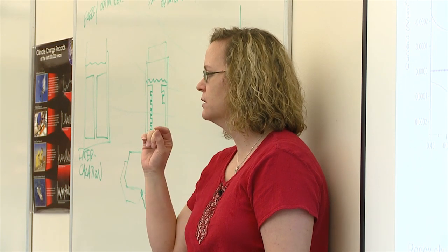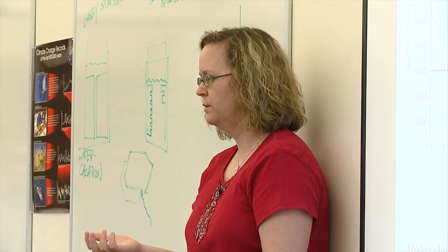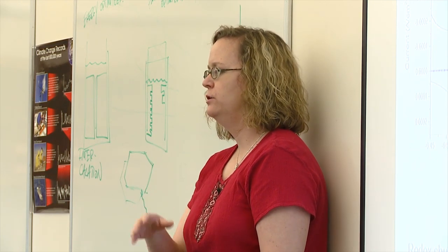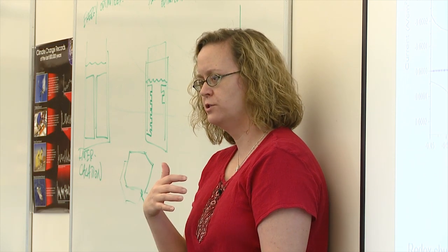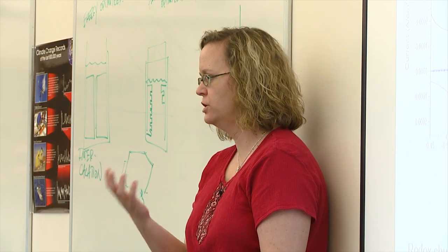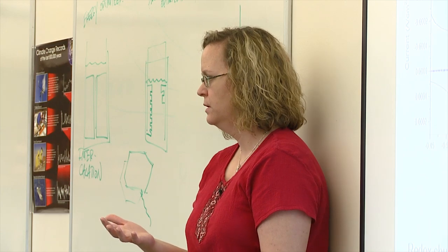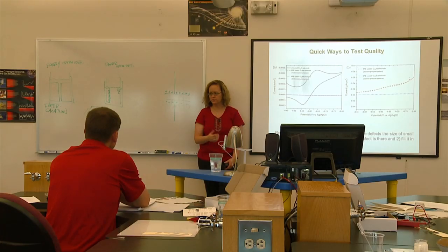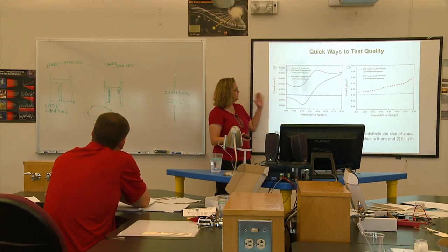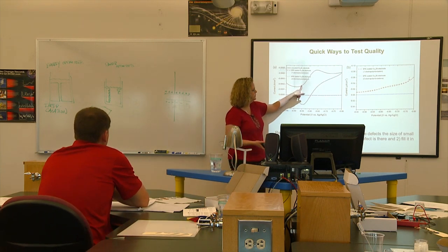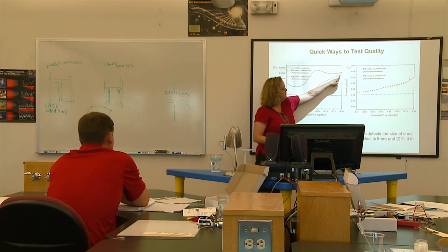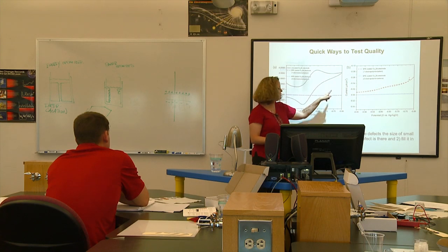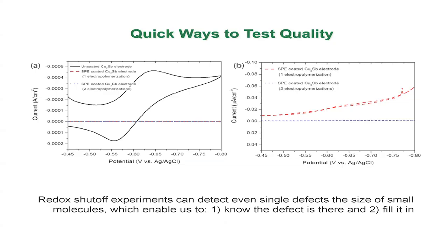So what we do is we take a small molecule that has really well-behaved electrochemistry. And when you scan in voltage and you measure current, you get this really typical shape that's often called a duck shape. So this experiment is called cyclic voltammetry. So on a plain electrode, this is what I mean by a duck shape. You see a peak here and it drops off. Then when you scan back, you should see the reverse of that. You see a peak here and it drops off.